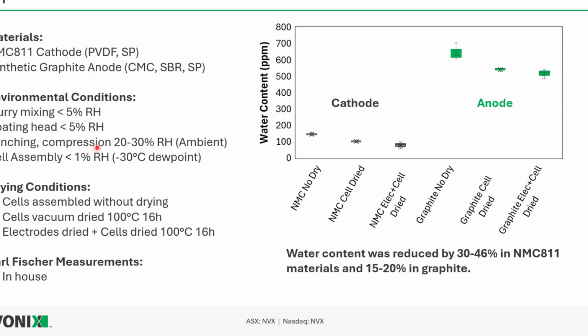Punching, compression, those in-between steps from coating into really assembly and welding, etc. This is where we have a little bit of exposure to ambient environment, which this time of year in our facility, which we control as best we can, is about 20 to 30% relative humidity. And then cell assembly, we're in a dry room with a minus 30-degree dew point.